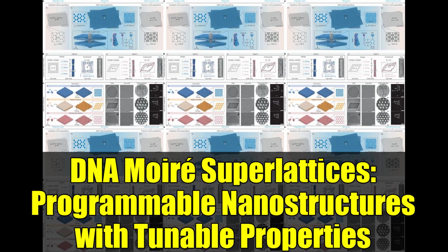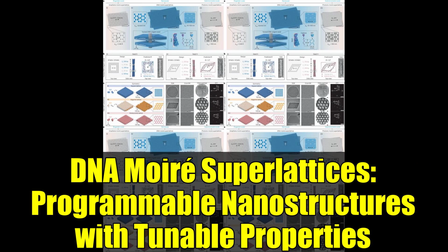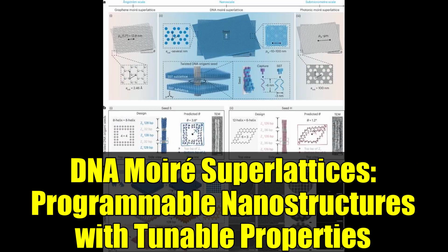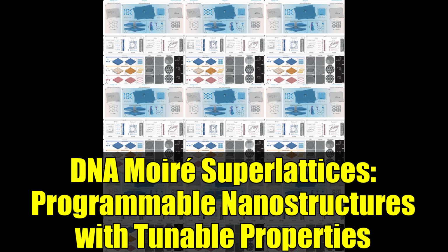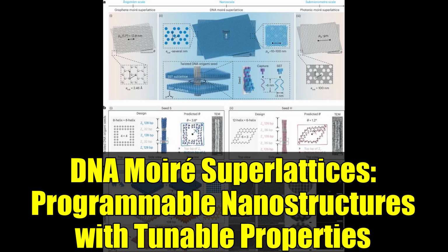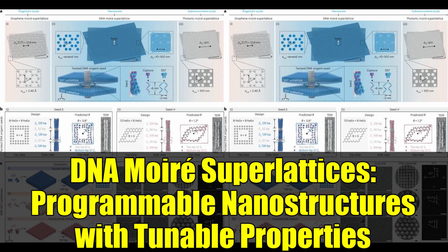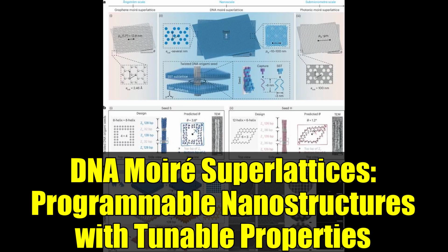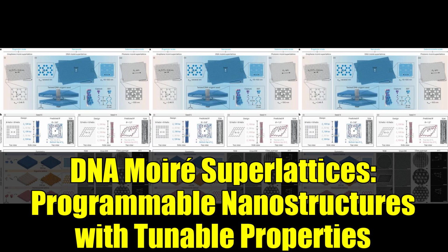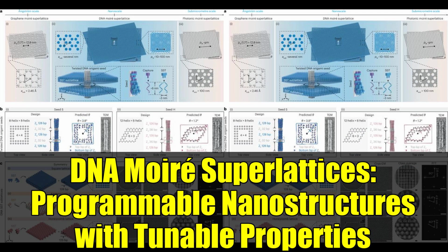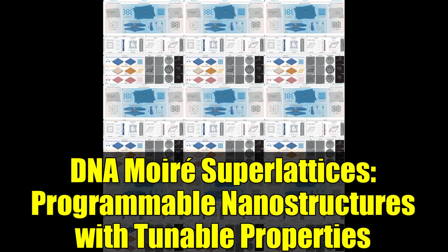Here's a surprising twist, pun intended. The size and quality of the resulting superlattices depend not only on these molecular details but also on concentration and temperature. Want mostly bilayers and fewer single layers? Use more seeds, but be aware, higher seed amounts nucleate more sites, yielding smaller superlattice domains overall. Lower temperatures mean homogeneous nucleation creeps back in, causing higher variability. Robust assembly, it seems, walks a fine line between temperature, seed design, and DNA concentration.